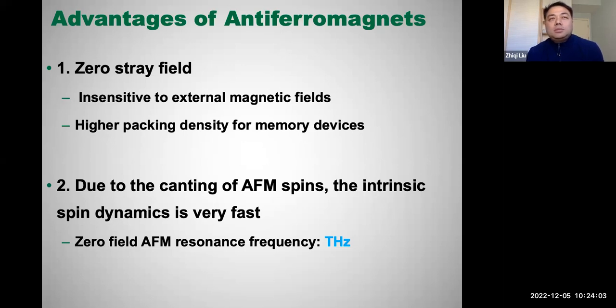This could be an advantage or a disadvantage. It depends on whether you try to store the information or try to write the information. On the other hand, due to the canting of antiferromagnetic spins, there is a so-called antiferromagnetic exchange interaction. The intrinsic spin dynamics for antiferromagnets is very fast. It could be 3 orders of magnitude higher than that of ferromagnets. It can simply reach terahertz.